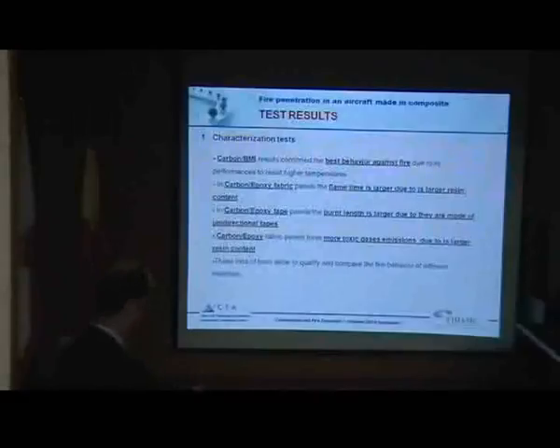So, well, mainly PMC 6 and 7 are the carbon fiber with this BMI resin, and you can see that they have the better results in heat release, also in optical density, and with less concentration of toxic gases, especially in sulfur dioxide. So the BMI resin presents the better behavior compared with the epoxy fabric and epoxy tapes. Those are the main conclusions they have remarked.